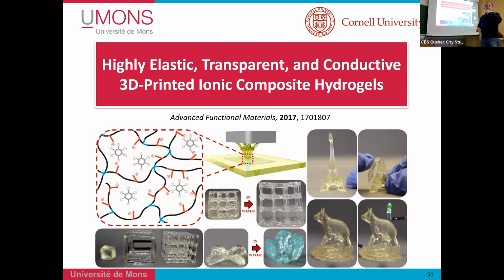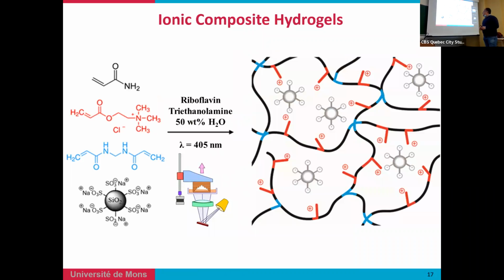Another example, if I have enough time to present, is developing ionic composite hydrogels mentioned here. The idea is to have an ionic gel combining two features: a gel, or the polymer backbone, brings some ammonium along the system, where we incorporate silica particles having a certain complementarity in terms of ionicity, in this case ion based on sulfonic moieties. Based on that, as I've already shown in some examples, you can have ionic interaction that can modify the properties.